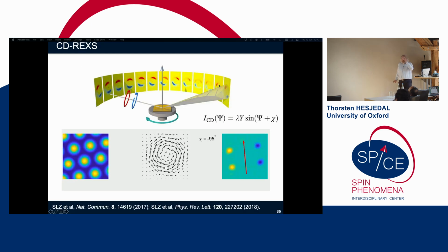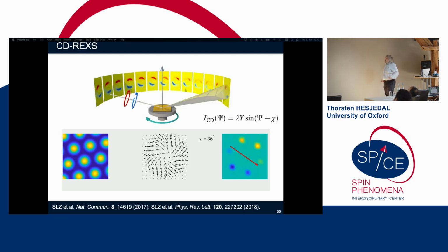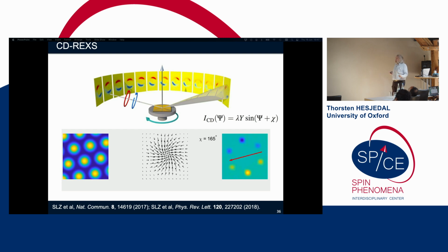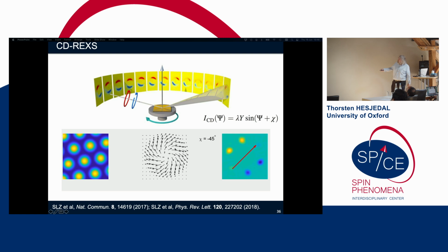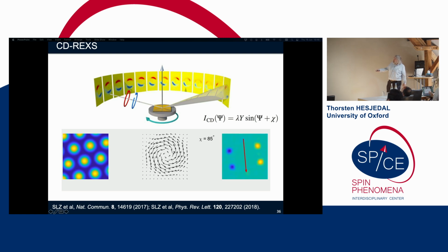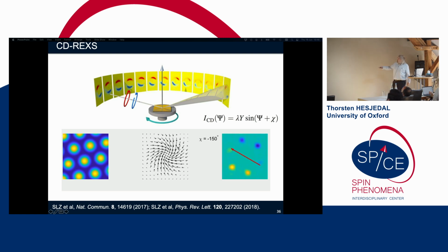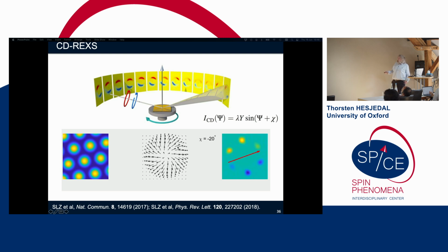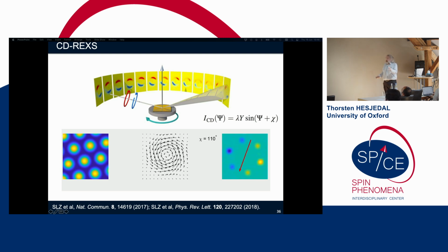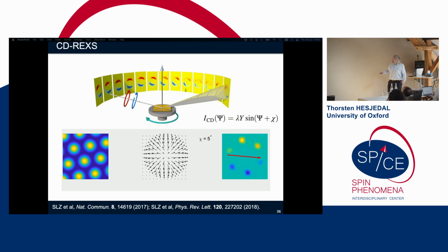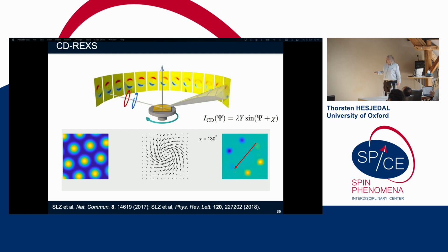Okay, wonderful. So if we put this together, then this is what we get for the Skyrmion lattice, now using, again, circular polarized light. And you can see here that there's a one-to-one correspondence between the helicity angle that now goes from Néel type to Bloch, to minus 90, back to Néel and back to Bloch again. And you can see that we call this the extinction vector. So it's the dividing line between, say, positive and negative dichroic contrast, right? So determining that allows us to determine the helicity angle in the system.